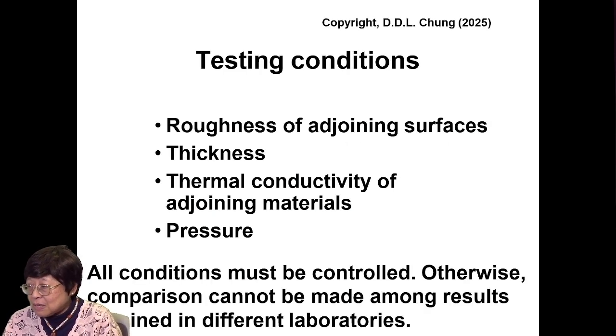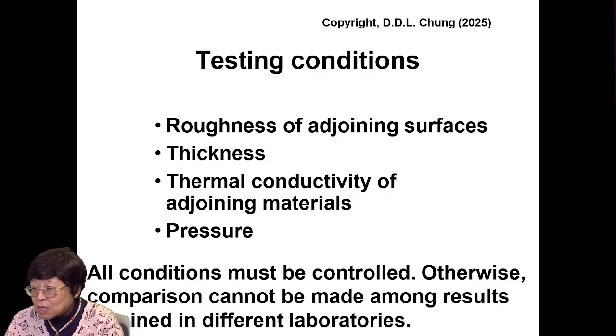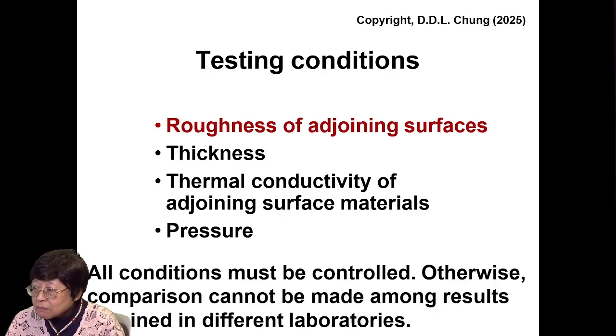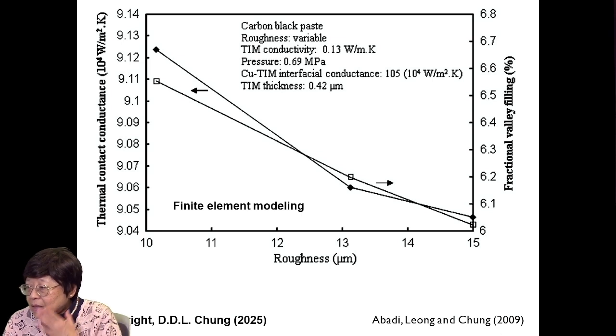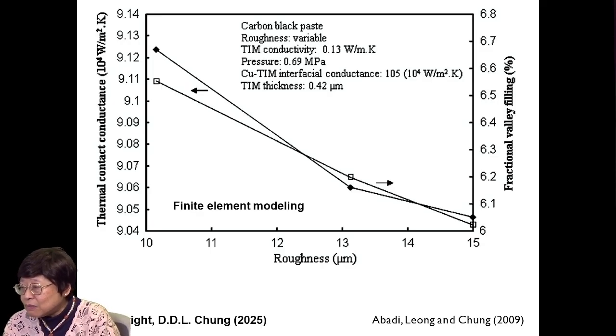The testing conditions include these: the roughness of the adjoining surfaces, the thickness, the thermal conductivity of the joining materials, and the pressure. All conditions must be controlled, otherwise comparison cannot be made among results obtained in different laboratories. First, consider roughness of the adjoining surfaces. This shows the thermal contact conductance versus the roughness with all other conditions fixed. And you can see that the greater the roughness, the smaller is the conductance, and also the smaller is the fractional valley filling.